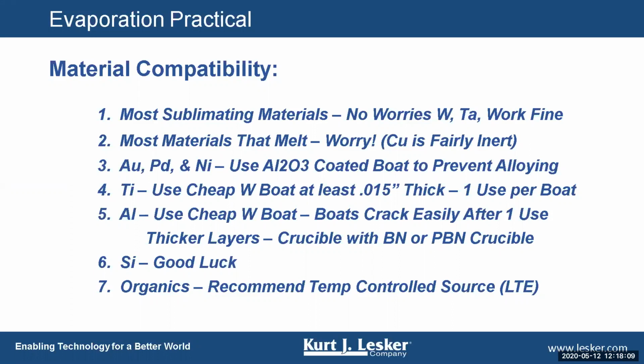Some materials are ill suited for evaporation, and silicon is one. Silicon in any shape or form is going to interact with any boat material once it starts getting hot and molten, and it will totally destroy boats, crucible liners, anything in its path. Once it's melted, it'll destroy.